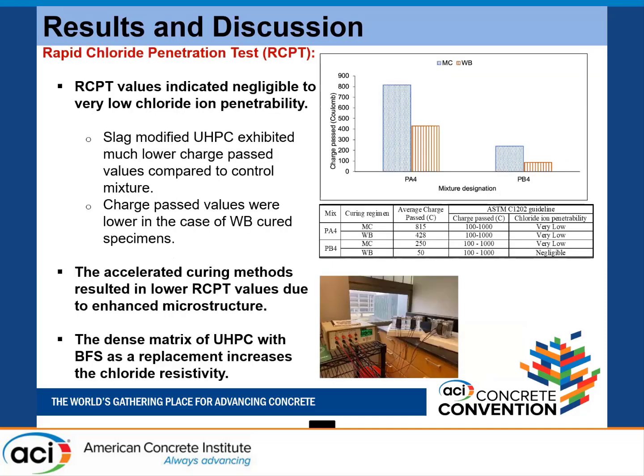And we performed the rapid chloride permeability test to observe the susceptibility to chloride ion penetration. If you look at it, the blue bars are with moist curing, and the orange bars are with water bath curing. Obviously, water bath curing at elevated temperatures accelerates the early action of the pozzolanic material. Early hydration of this pozzolanic material, slag, produces secondary calcium silicate hydrates that fill the voids left from the primary hydration of cement, so that enhances the microstructure. So obviously the pore spaces and pore volumes have been reduced. Therefore, the chloride ingress is reduced. In both non-slag mixes and slag mixes, we observed very low to negligible chloride ion susceptibility.